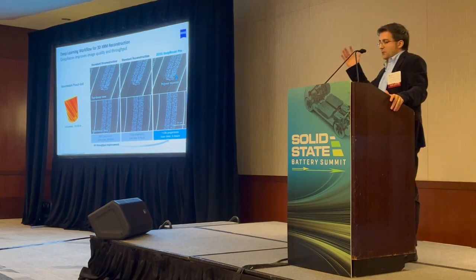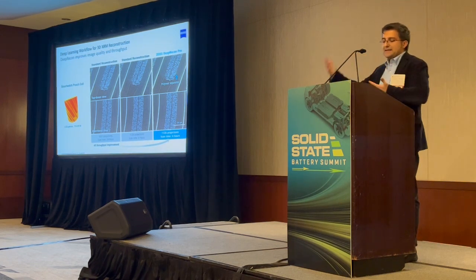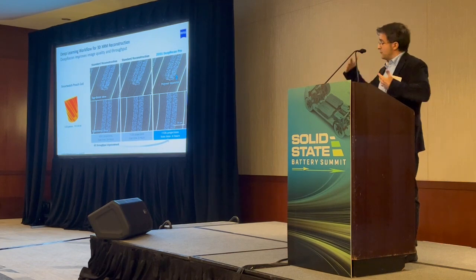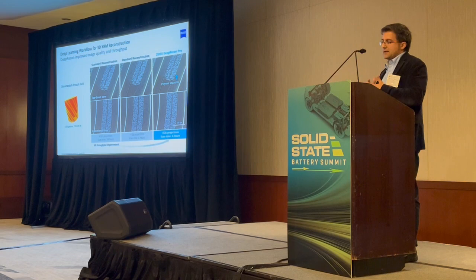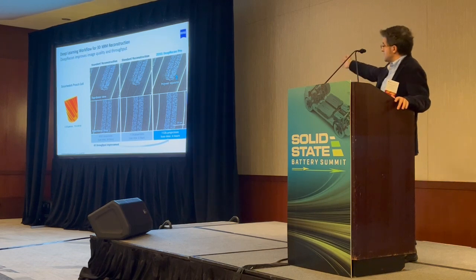This is an example of an intact lithium battery from a commercial smartwatch. The regions of interest are typically the cathode materials, particle structures, debris, or any potential damage in the polymer separator. And DeepRecon demonstrated that it can get a 4x throughput time improvement in this case, and even some improvement in image quality, as you can see in the last image.